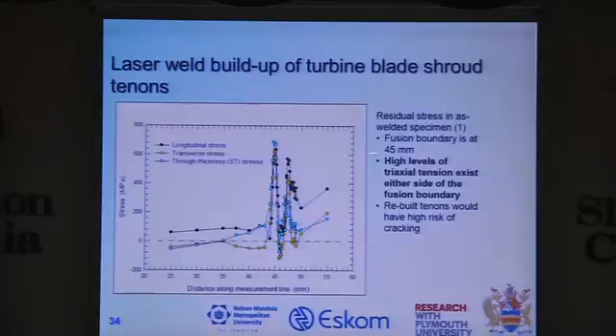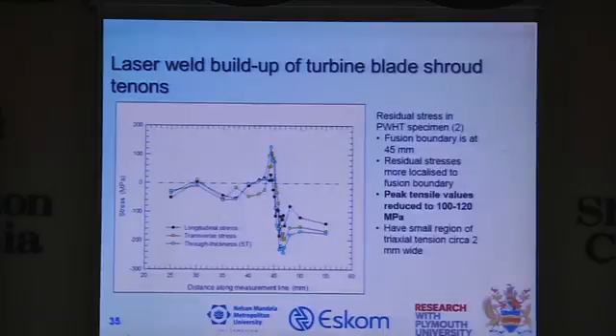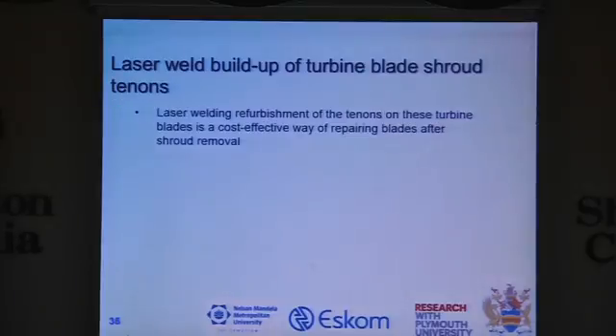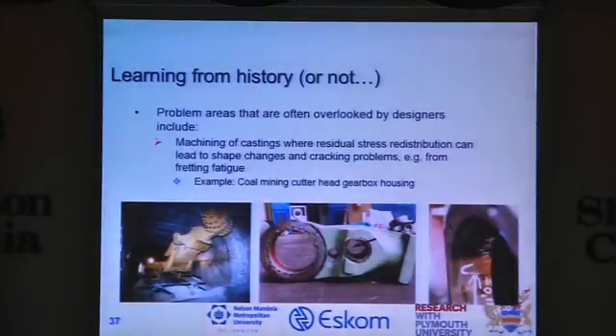There's the tenon, and you have very high triaxial residual stresses at the fusion boundary on both sides of that laser weld. So really, immediately from this data, we say we've got a very high risk of cracking. However, if you heat treat these samples properly, you can get the residual stresses normalized in a certain way. And again, now you have the confidence that you've got a process that is sound, homogeneous, and of which the residual stresses are understood well, you can apply. So again, this we have not applied in industry, but when the time arrives, we are ready now to implement it.